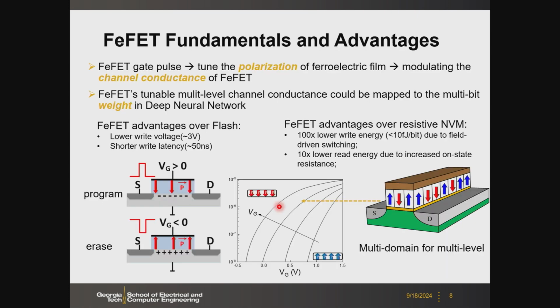So here are some fundamentals of the FE-FET. We already mentioned that before, but if you look closer at this cartoon figure, if you program the ferroelectric, let's say apply a large enough positive gate voltage, you can polarize all the dipoles down. Those dipoles will easily induce inversion of the channel. Then you get electrons in the channel, which means your threshold voltage is lower. If you look at the ID-VG, it should be something like this.